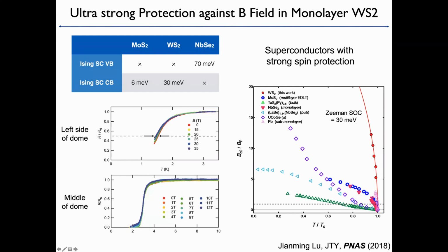So if we analyze this behavior, we can actually compare with all the existing highly protected superconductors. Some of these are the TMDs previously studied, and also niobium diselenide with this Ising type protection, and some heavy fermion that is protected by the Rashba effect. Compared with them, this is definitely much stronger, and we cannot even measure more data points because of the limitation of the static B field. So this is definitely larger than 10 times the Pauli limit. That's what we can say for these data points.